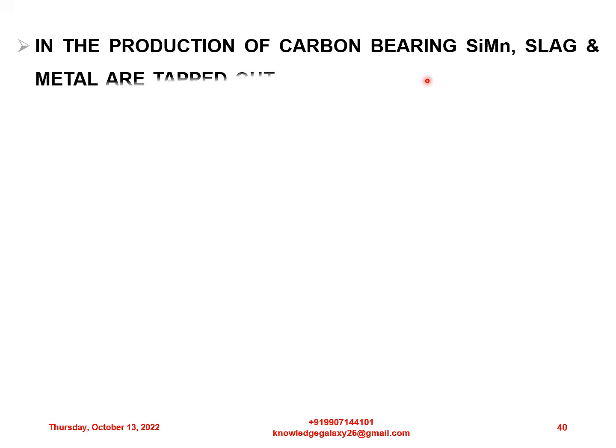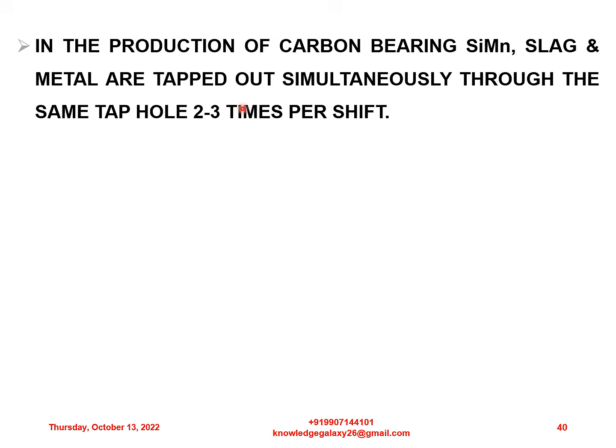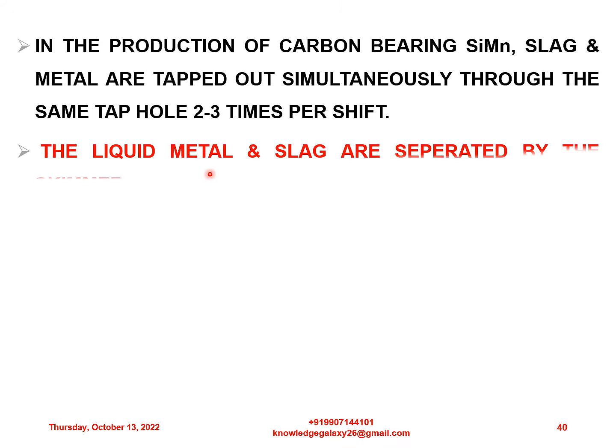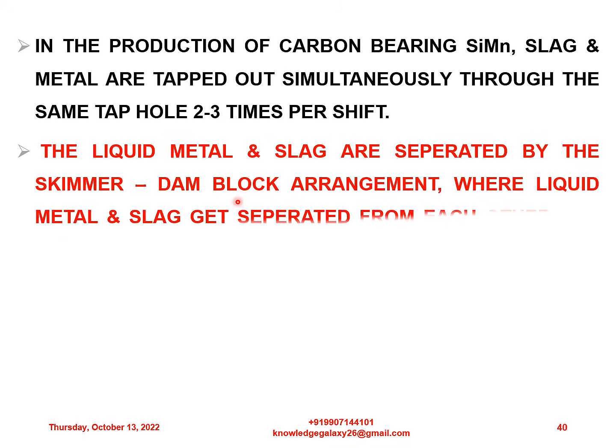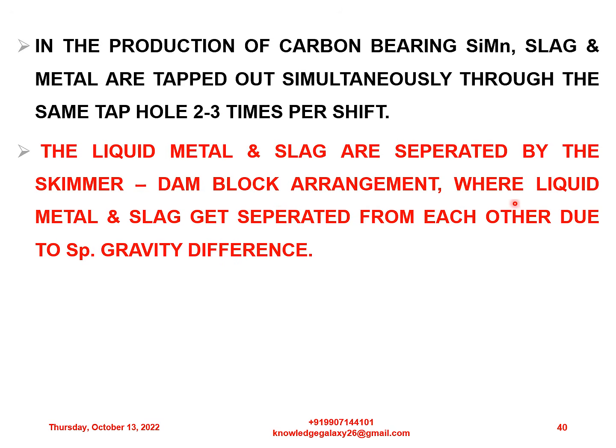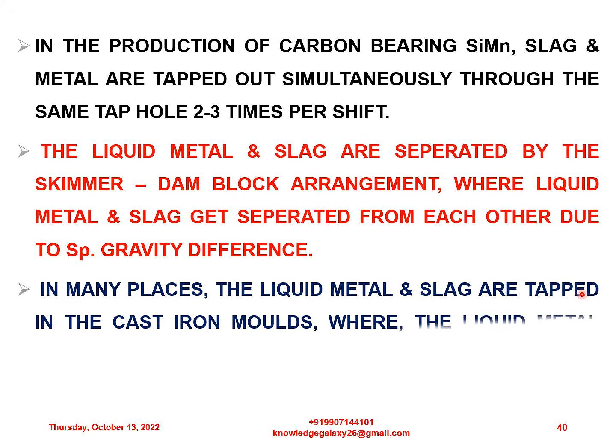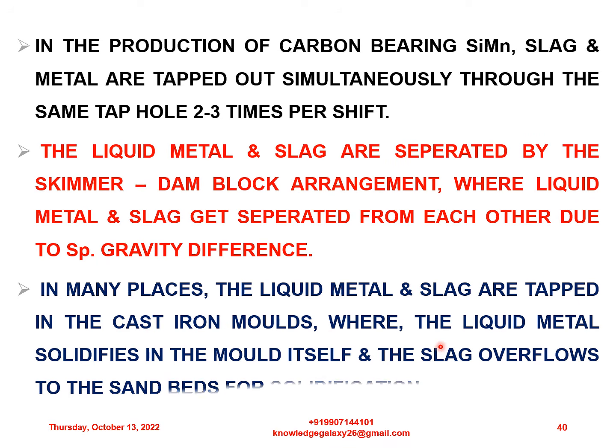In the production of carbon-bearing silicomanganese, slag and metal are tapped out simultaneously through the same tap hole, 2 to 3 times per shift. The liquid metal and slag are separated by the skimmer dam block arrangement, where liquid metal and slag get separated from each other due to specific gravity difference. In many places, the liquid metal and slag are tapped in cast iron molds, where the liquid metal solidifies in the mold itself and the slag overflows to the sand beds for solidification.